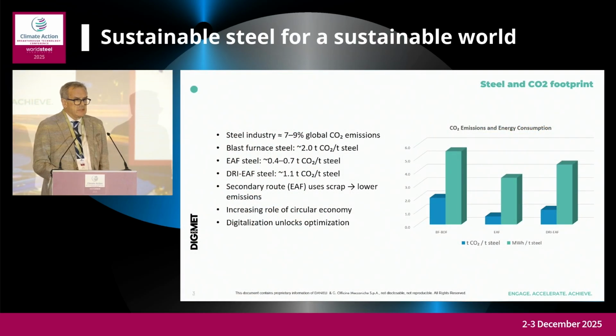Steel production accounts for roughly 7 to 9% of CO2 emissions. Everybody before me already confirmed this value. Basically, blast furnace, basic oxygen furnace routes emit roughly 2 tons of CO2 for each ton of liquid steel. And electric furnaces, which are most of the time fully scrap driven, emit significantly less, about 0.4 to 0.7 tons for each ton of liquid steel.